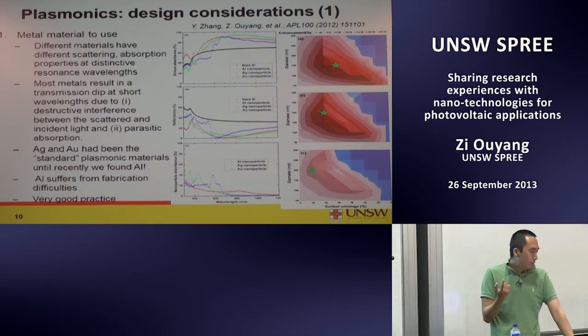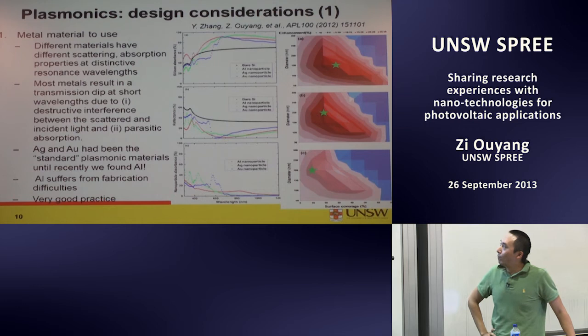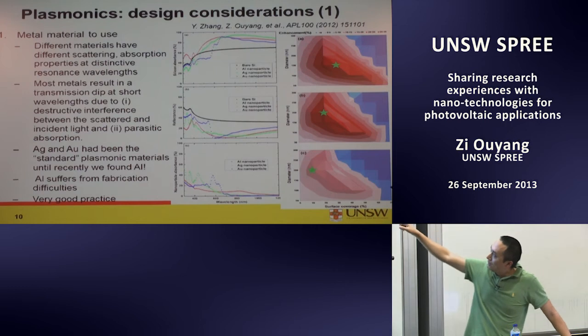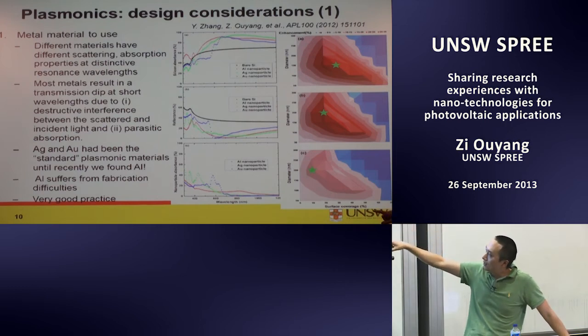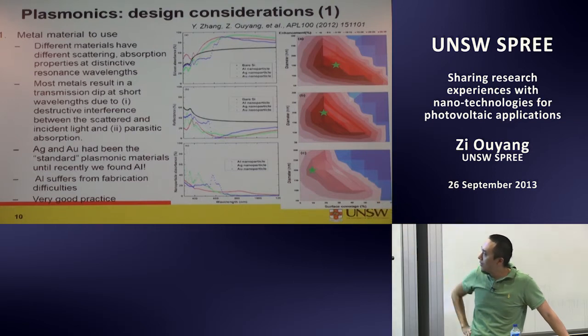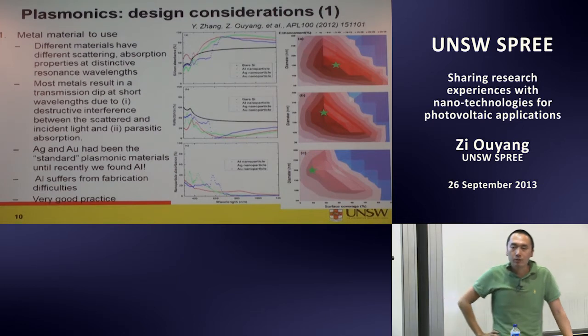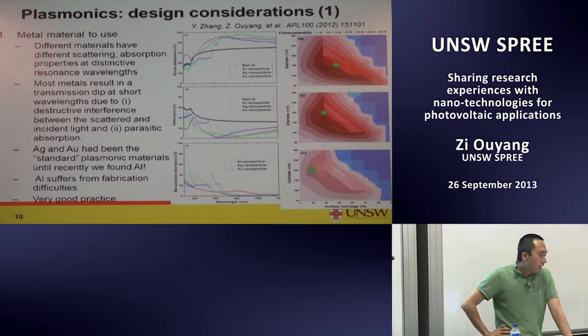So the first thing we need to think about is what metal material are you going to use? Different materials have very different properties. If you look at the reflectance curve and the nanoparticle parasitic absorption curve, they are very different. Now we're comparing silver, gold, and aluminum nanoparticles with the same diameter. They are different because they absorb the light at different levels, and they have different sorts of interference with the incident light.